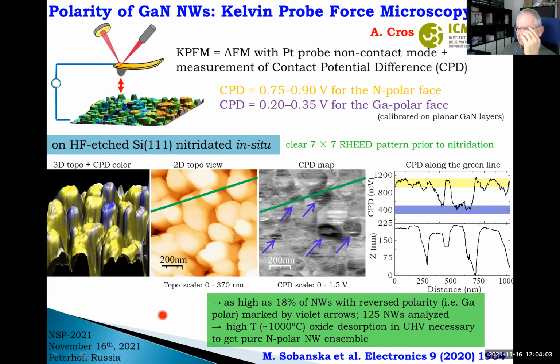And in this work, we checked several recipes of cleaning the silicon substrate prior to growth, using RCA clean, gallium cleaning, deoxidation in gallium flux, etc. They help, but the best results, very complete elimination of the mixed polarity effect, we obtained only when using high temperature oxide desorption under ultra high vacuum. So a clean surface, when you just have a wafer from a good vendor, and without any treatment, you just dissolve the oxide from the surface. You need a high temperature heater, which is not always available in an MBE machine, but it really works.